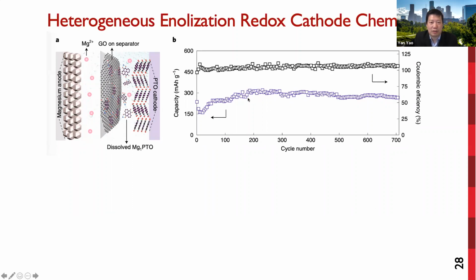First, the solubility of magnesium 2 PTO actually is less than 1 millimolar. So this is 100 times less than that of polysulfide. Dissolution of PTO is suppressed by inserting a 2 micrometer thin lightweight graphene oxide membrane between the cathode and the separator to trap the magnesium 2 PTO intermediate, but still maintain electric contact because this graphene oxide membrane is electronically conductive. So all the capacity trapped by the Mg2PTO can still contribute to the capacity of the cathode. This concept is borrowed from lithium sulfur battery and has been proved very effective.